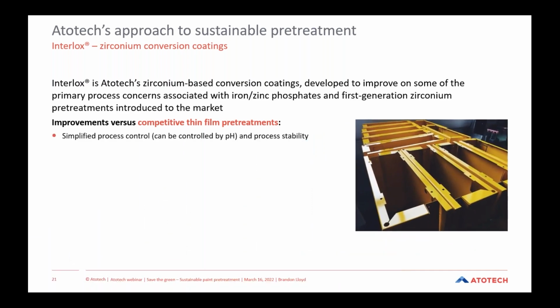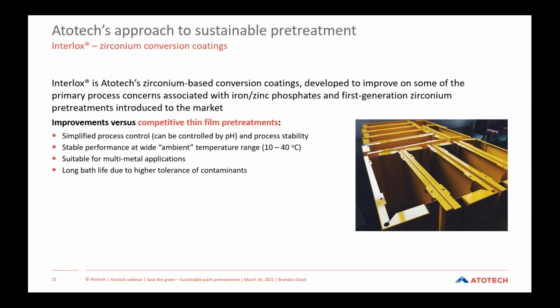When we compare Interlox to some competitive thin film pretreatments, some of the process advantages typically observed include simplified process control. Here, Interlox can truly be operated by controlling the pH of the process itself, as well as the process stability. They do offer a stable performance at a wide ambient temperature range. And for us, we consider an ambient temperature range for our Interlox conversion coatings ranging most normally from 10 to 40 degrees Celsius, but can be operated even at lower temperatures as well without impacting the overall process or part quality. They are, again, suitable for multi-metal applications. They do improve on the bath life as they have a higher tolerance for contaminants.